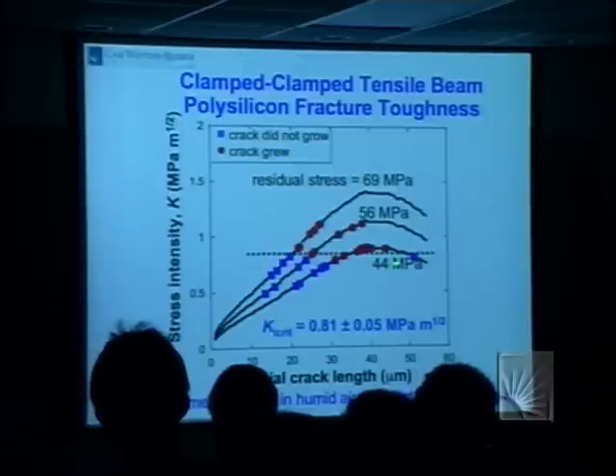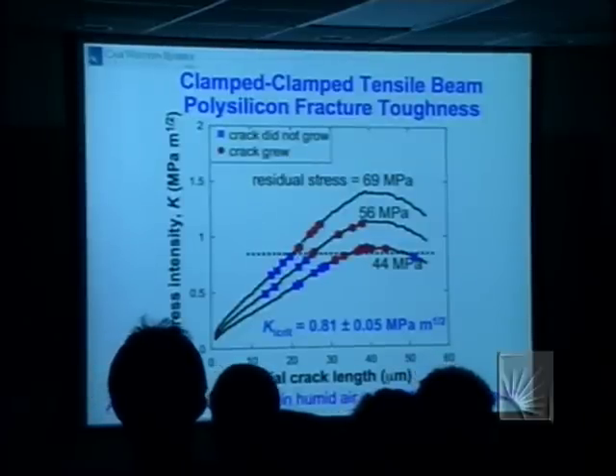It's interesting that there was one device of this length that didn't propagate to failure, and it's pretty clear that this crack propagated and then arrested as K fell below K1C, which is just what you'd expect in a fixed grip test. Okay.